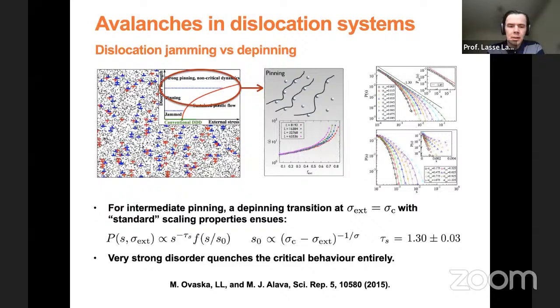Then we can also in principle look at what happens if you add some additional defects in your system. So some pinning points interacting with the dislocations. This could change the nature of this fluctuating dynamics a little bit. So instead of this kind of a jamming, you actually have a process which looks more like a typical phenomenon of depinning transition. So you can think of like some elastic manifolds in random media, like domain walls or cracks or whatnot. So the scaling picture will look more like that. Of course, here I'm not going to actually look into that too much. So that's just kind of an anecdote here.